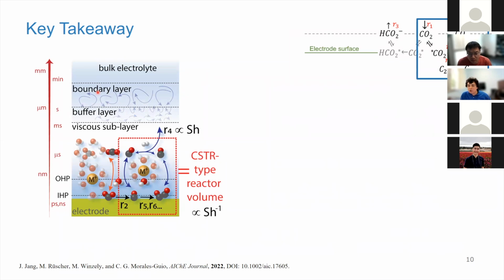So it so happens that in CO2 electrocatalysis, we start from carbon dioxide that comes from the bulk of the electrolyte. It diffuses, it travels all the way through different layers of the electrolyte. Once the carbon dioxide gets to the surface, you make carbon monoxide. And then that carbon monoxide is limited by its solubility in the liquid, which is quite low. Typically, with reaction intermediates in electrochemistry, if the molecule has no solubility problems, you expect it to dissolve and travel away. But for CO2 reduction on copper, carbon monoxide binds quite strongly to the surface. So you keep a high surface coverage of CO, and some of that CO still dissolves, but it comes back and reabsorbs because it cannot be transported away at a fast enough rate.